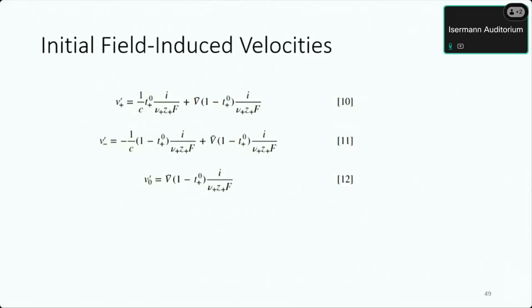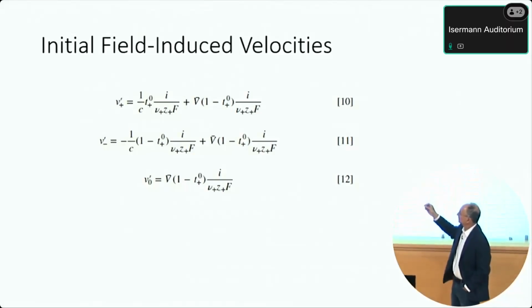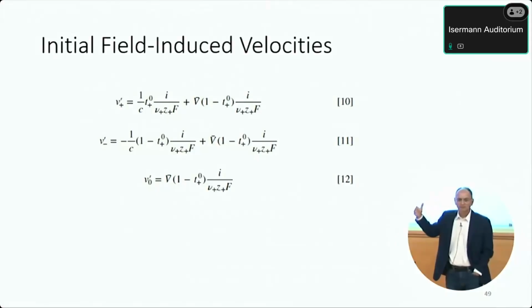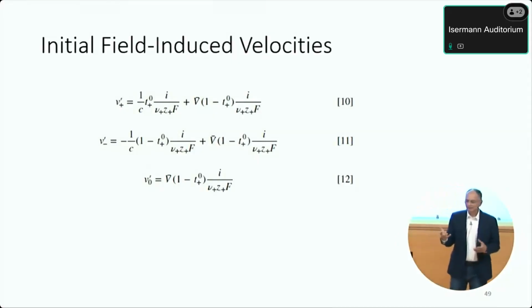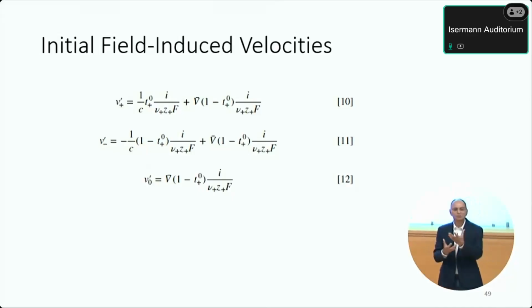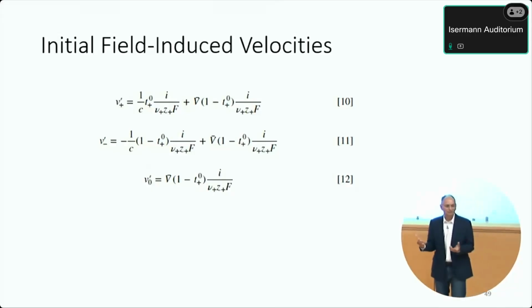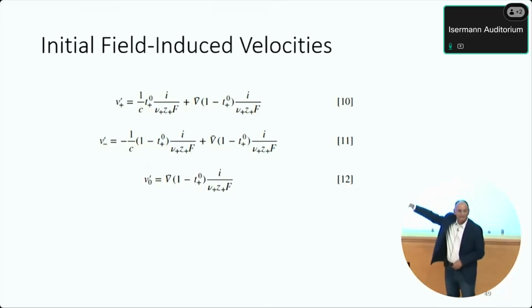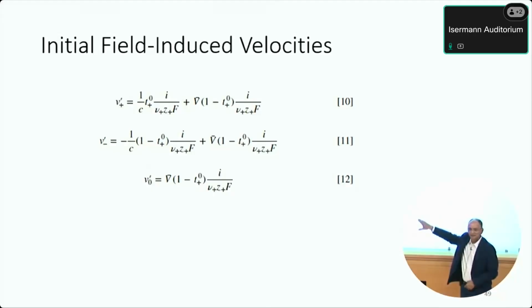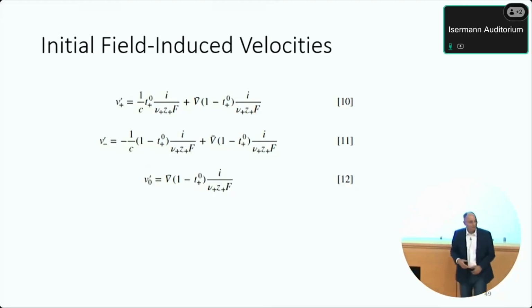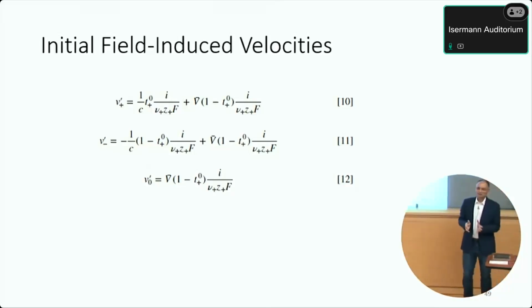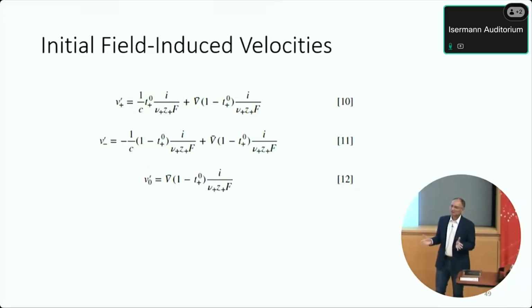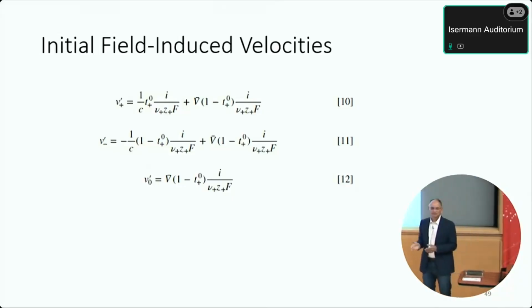So, for example, if you know the transference number T plus 0, the solvent velocity is fixed. V bar turns out to be the partial molar volume of the solid. So folks, it's very simple. If you have a cation and anion, and the field makes them move, and the volumes are not identical, the solvent has to do something. The solvent rearrangement has been around for a long time, and even something simple like this has not been in the literature. V0 has been assumed to be 0 when T plus 0 is not 1. When the transference number is 1, it means only the cation moves, and there you're all golden. But if the cation and the anion move, the solvent has to move. And in hindsight, this is not rocket science.